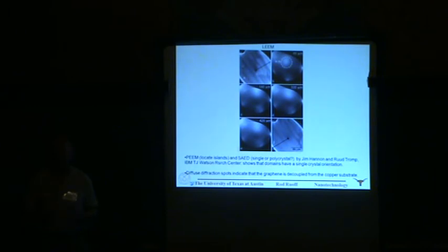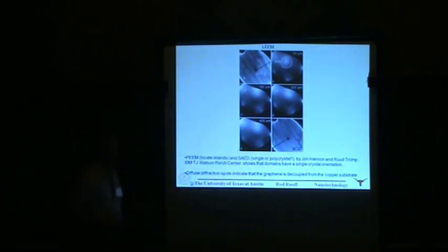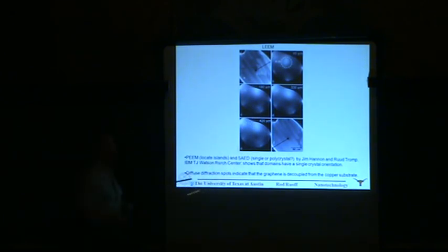And we don't yet capture nucleation events, which are happening with very small clusters, probably around C20 or so, because we don't have that length scale in batch experiments. We see islands, like I'm showing you now. So we also collaborated with colleagues at IBM. Ruud Tromp is one of the world's experts in low energy electron microscopy. They identified where the flakes were, and then they used selected area electron diffraction.